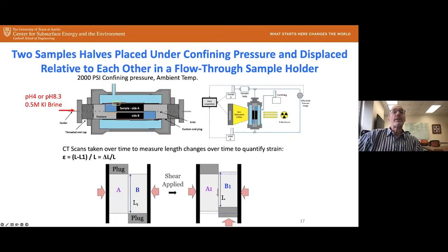So we took these two sample halves, let's say side A and side B of the core. We have the interlocked asperities. We put it in this custom triaxial core holder. This was done at NETL. We put it under 2000 PSI confining pressure. We crank a screw, it presses one side of this and displaces it relative to the other side. So here's our two halves. We have the two plugs on either side. When we turn the screw, it moves one side relative to the other, creating this strain, which can then be released over time. All right.